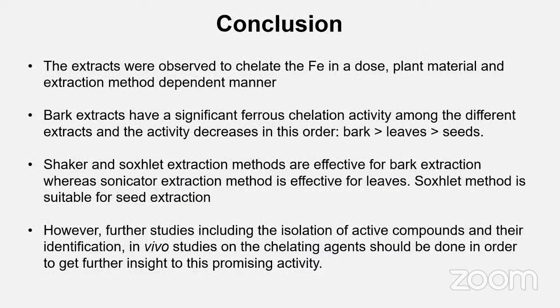According to the results, there are some conclusions we can mention. The extracts were observed to chelate ferrous ions in a dose-dependent manner, and dependent on the plant material and the extraction method. Bark extracts have significant ferrous chelation activity among the different extracts, and the activity decreases in this order. The bark has shown promising activity, marginal activity can be observed with the leaf extract, and the seed gave weak activity.